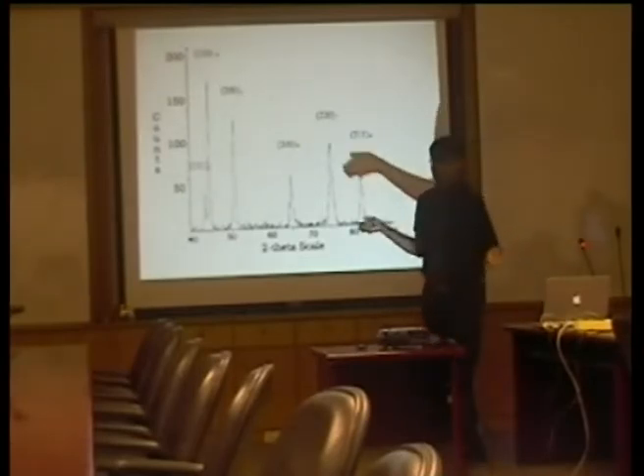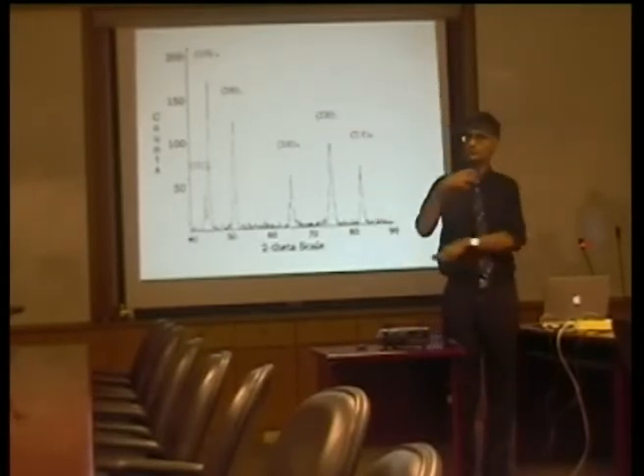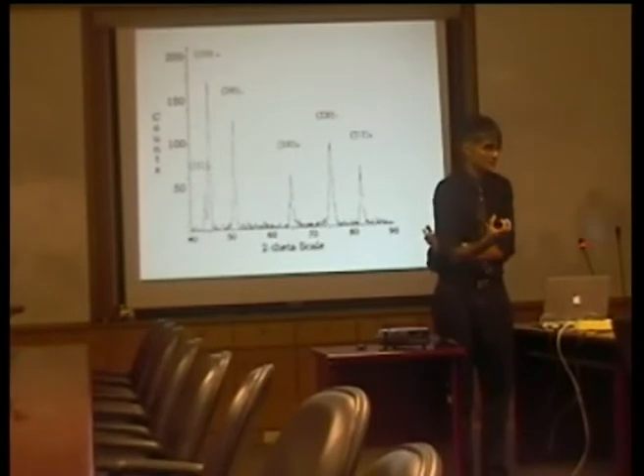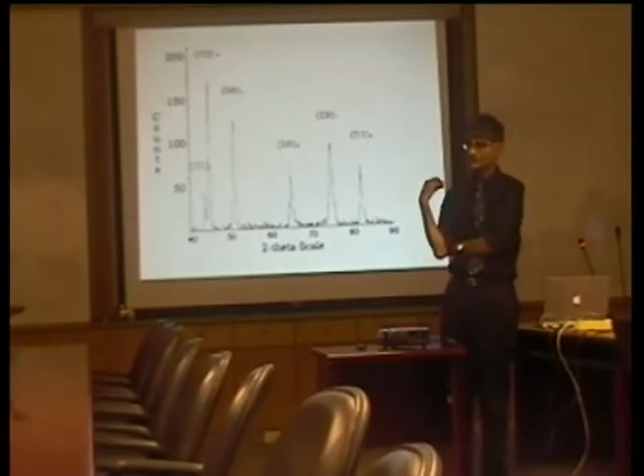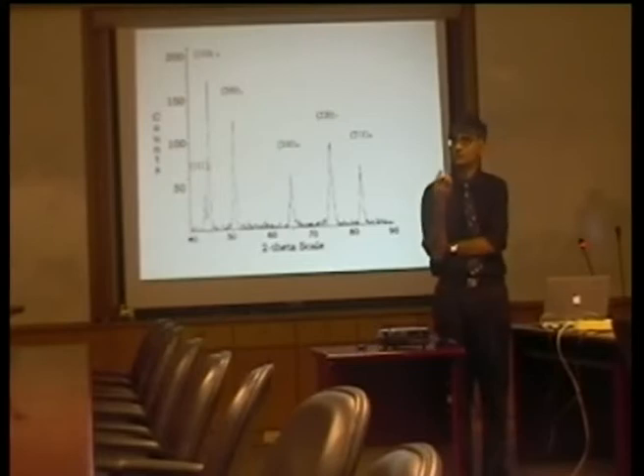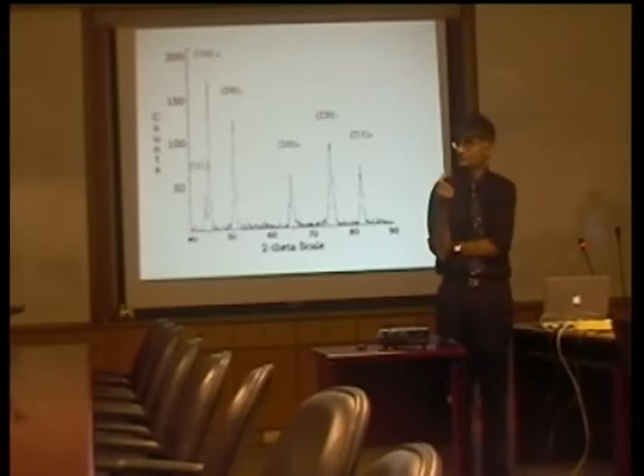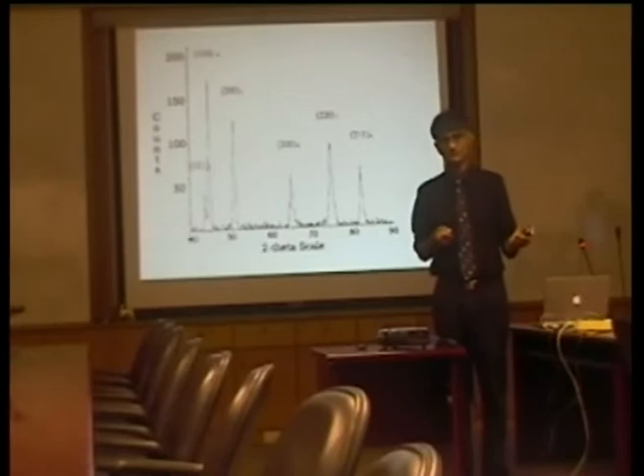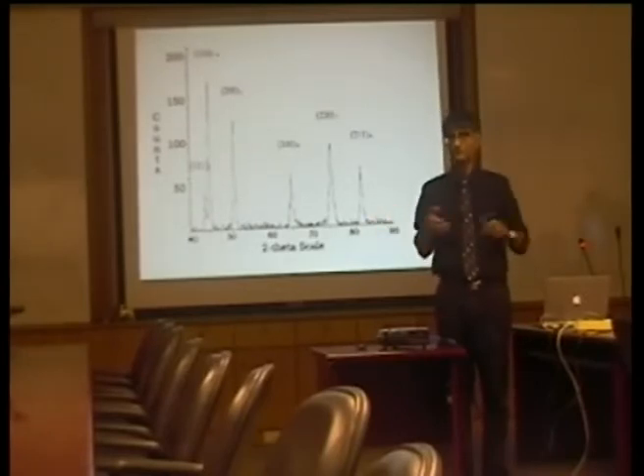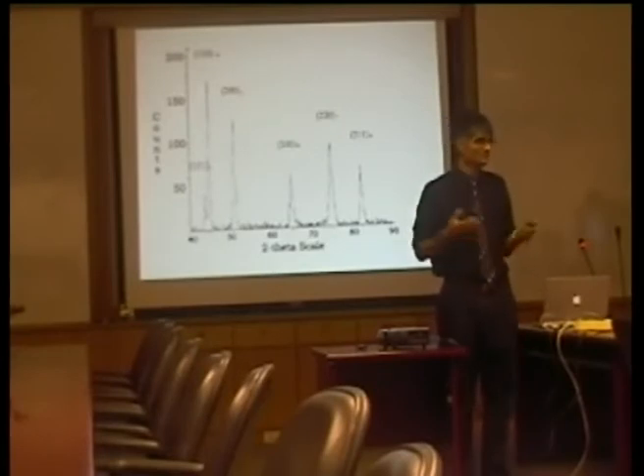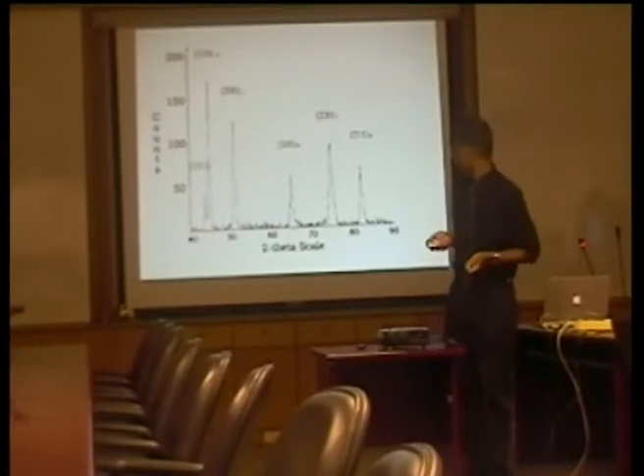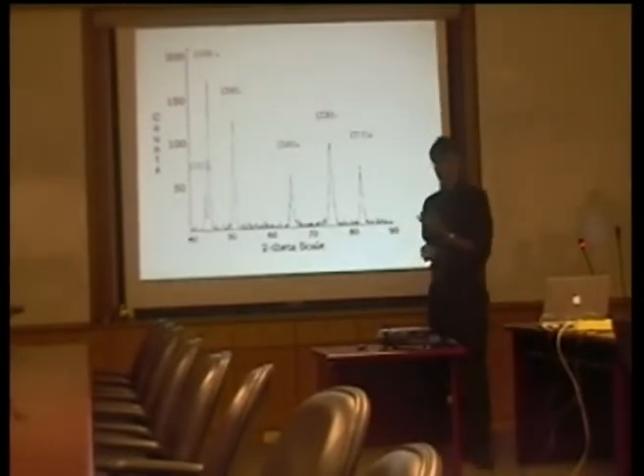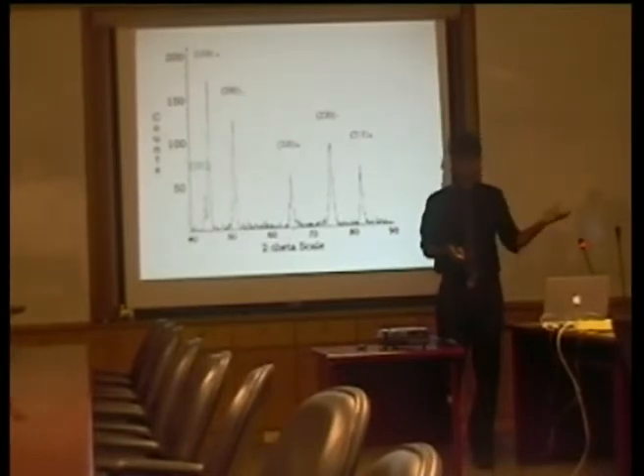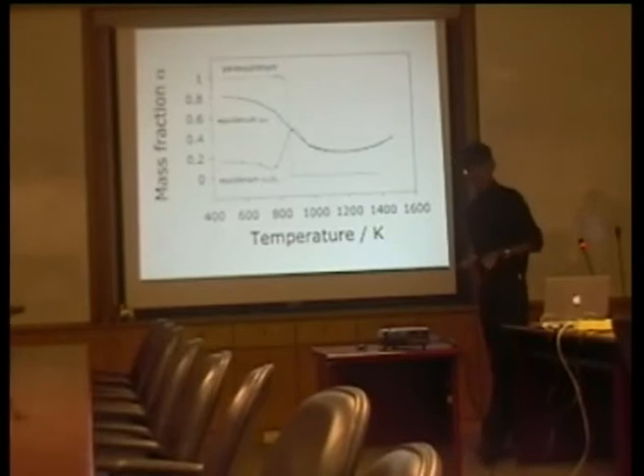So the reason for doing X-ray diffraction was to get a quantitative number for how much martensite we have. And if you do a detailed analysis of these patterns, then there's about 57% of martensite formed after a true strain of 6. So very, very severe deformation, and it's only transformed to 57% of martensite. You would have imagined that you would get a lot more martensite after such a severe deformation. So that is a little bit puzzling. Why have we got so little martensite after so much deformation? Well, let's have a look at thermodynamics. Okay?